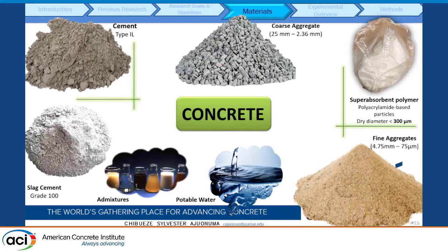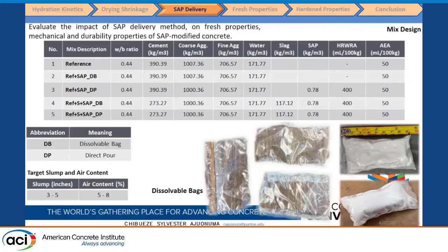So these are some of the concrete mixing materials we use, and then the mix design. For the laboratory experiment, we scaled down the bag, because that was a 1 pound bag for 1 cubic yard, but in the lab we don't need to make one cubic yard of concrete. So we scaled down the dissolvable bag by batching the quantity of SAP we needed. We had 5 mixes, where we had the reference mix. Then we added 2 delivery methods for the SAP, directly pouring the SAP and using the dissolvable bag. And also we did 30% of slag replacement, and then added SAP directly, and also used the dissolvable bag to be able to see that the dissolvable bag works effectively before we proceeded to the field trial.